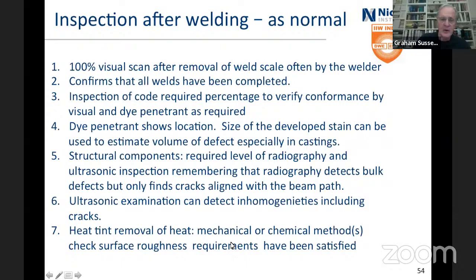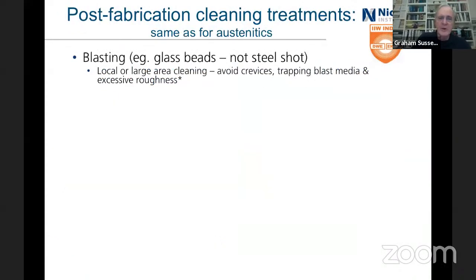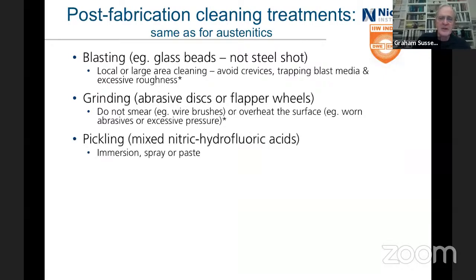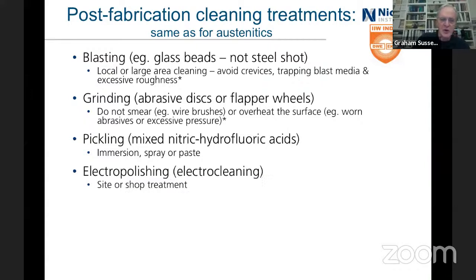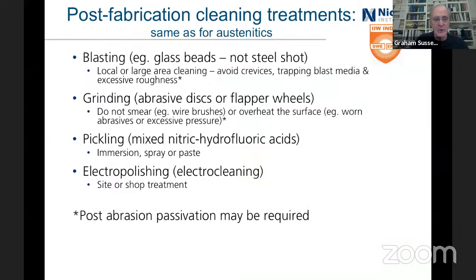And if you're going to do mechanical, then make sure that it's not rougher than it should be, because rough surfaces tend to be more corroded. And you can blast it, glass beads, abrasives, pickling. Love that hydrofluoric acid. Well, I don't actually, but still, it does a good job. And electropolishing. Electrocleaning using the carbon fiber brushes is something that really is used quite a bit now. The difficulty about it is that it's very, very operator dependent. And unfortunately, they tend to give it to the apprentice and they don't give him or her the training beforehand. And that's really necessary, but it does work reasonably well.